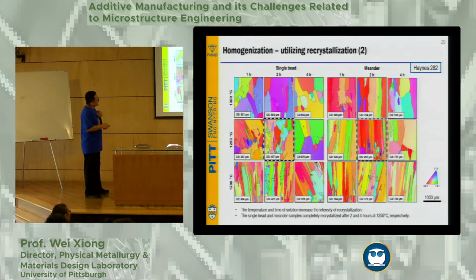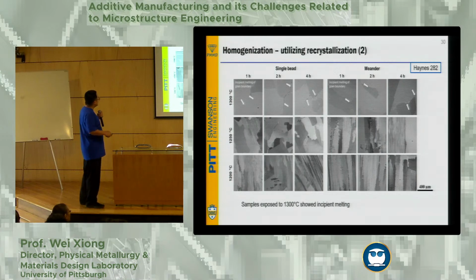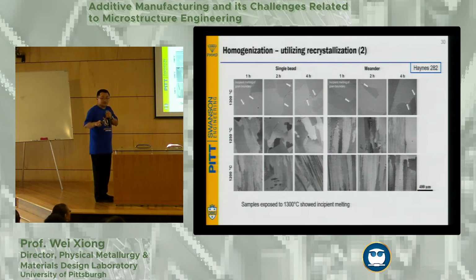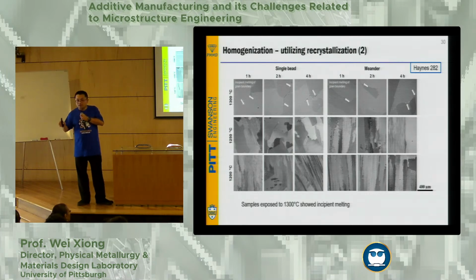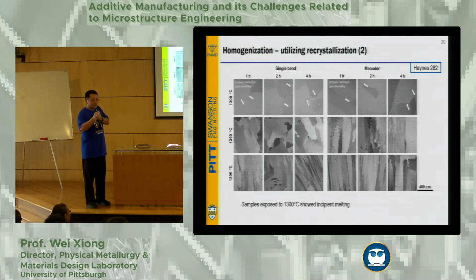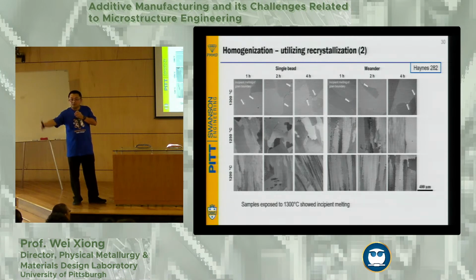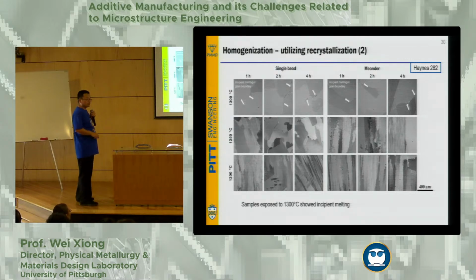So after doing heat treatment, as you can see, some fine structures actually happen, but not so pronounced. That's still good. So what we do is check in with the SEM, and as you can see, this confirms it. But another indication is if you look at these two different printing strategies, you have single bead and meander, because the initial introduced microstructure is also different. Therefore, even if you can promote the recrystallization process, you're not necessarily guaranteed that this recrystallization will help all the grain refinement introduced in this Haynes 282. It only happened more pronounced with single bead.